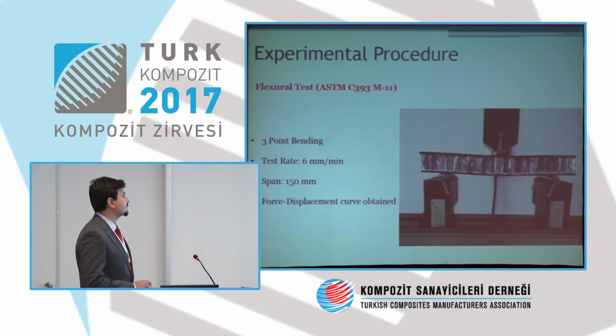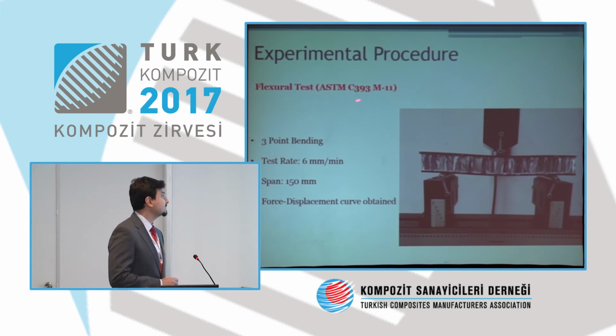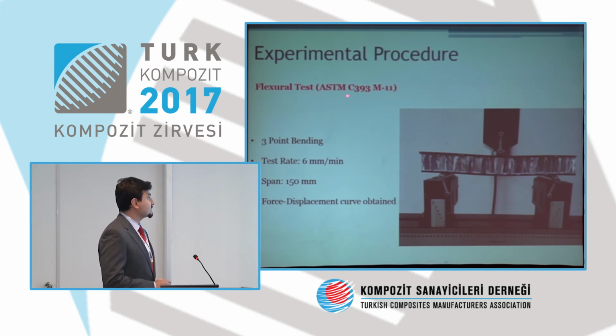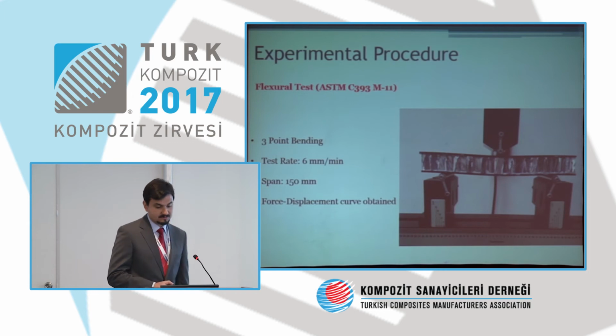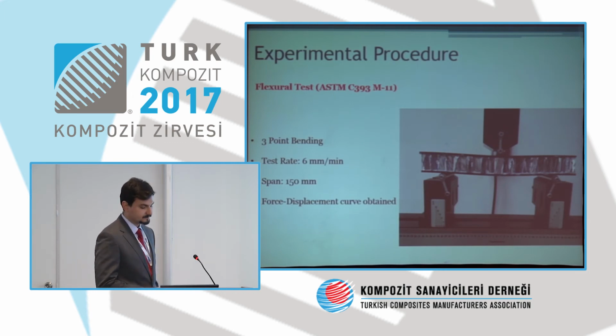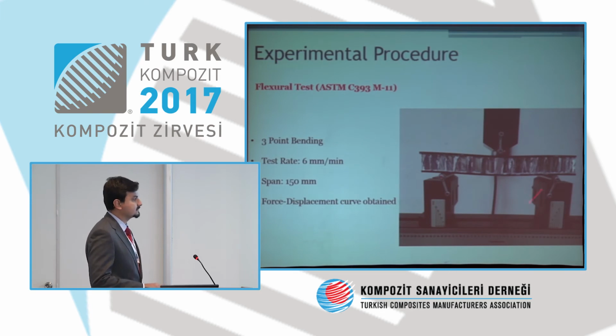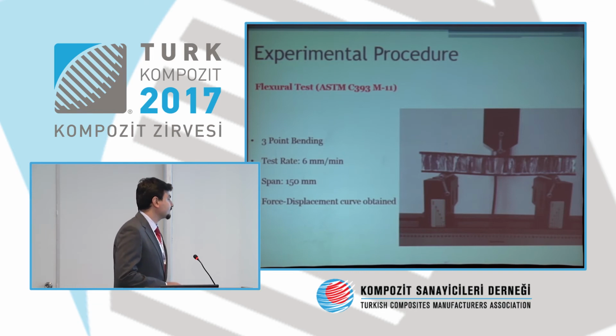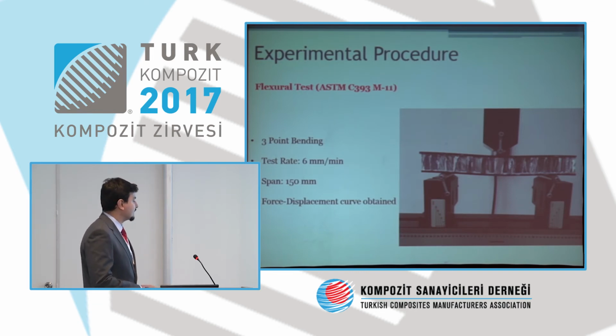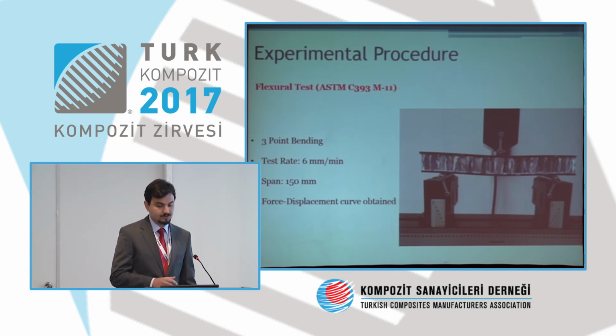And firstly, we did the monotonic flexural test according to ASTM-C 393 standard. Our load type is 3-point bending. This is our test setup also. Test rate is 6 millimeter per minute according to this standard. Span is 150 millimeter. And we obtained the first force displacement curve.